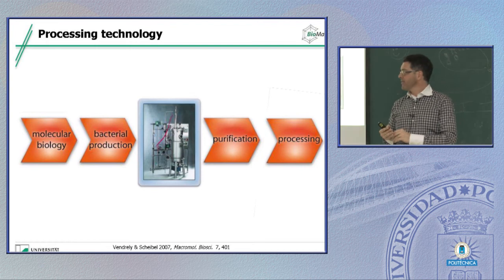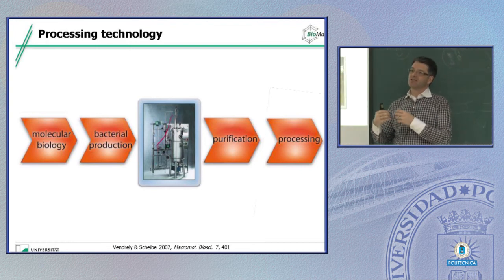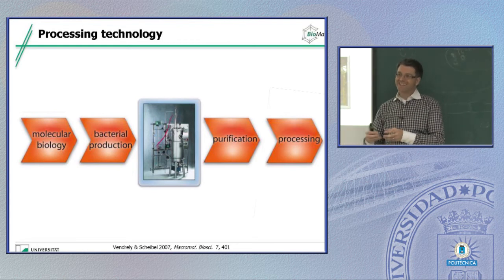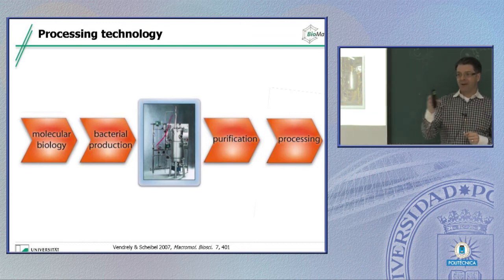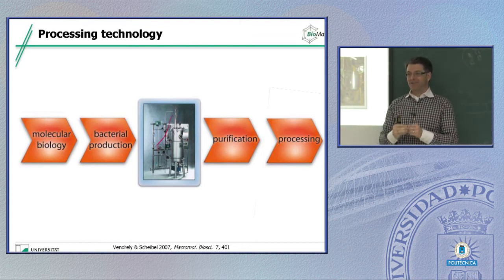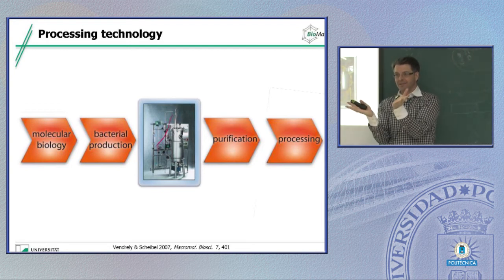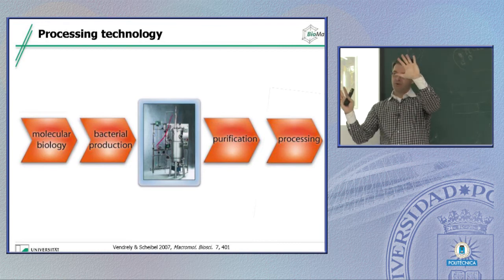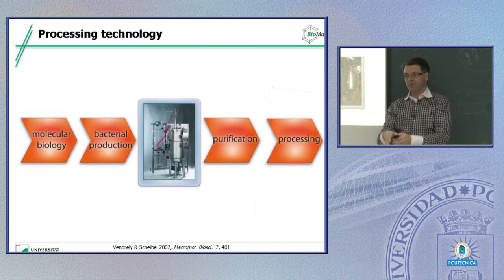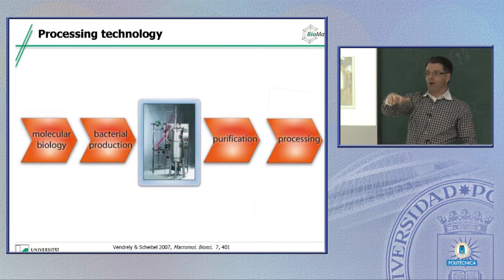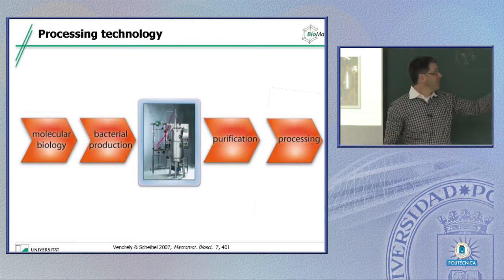And now we use something that makes silk so famous. It's very well soluble in water, and it does not aggregate. So you can boil the whole thing. So again, now we come to the egg problem. If we typically boil proteins, they unfold. The hydrophobic side chains are exposed, and they aggregate. When they aggregate, they fall out of solution. So if you open an egg and put that into boiling water, you get white flocks, and they just sediment.